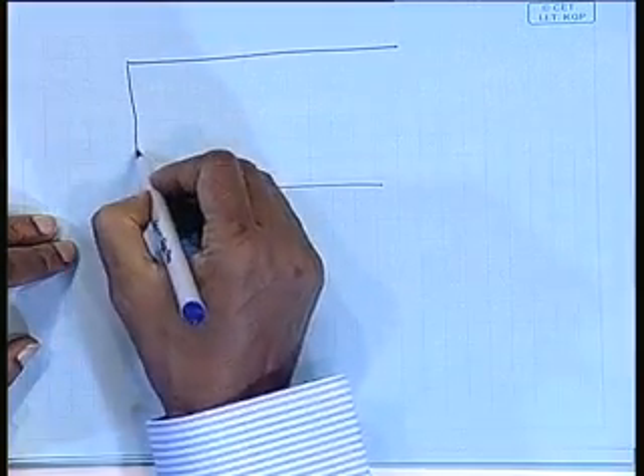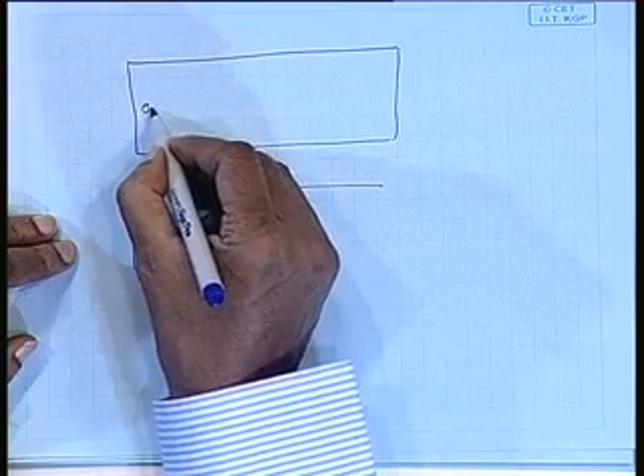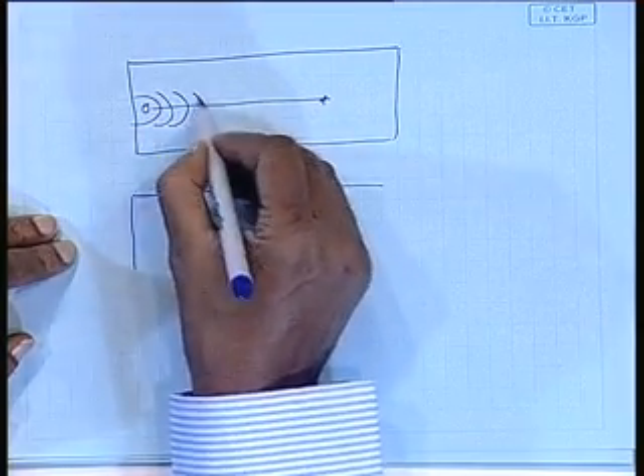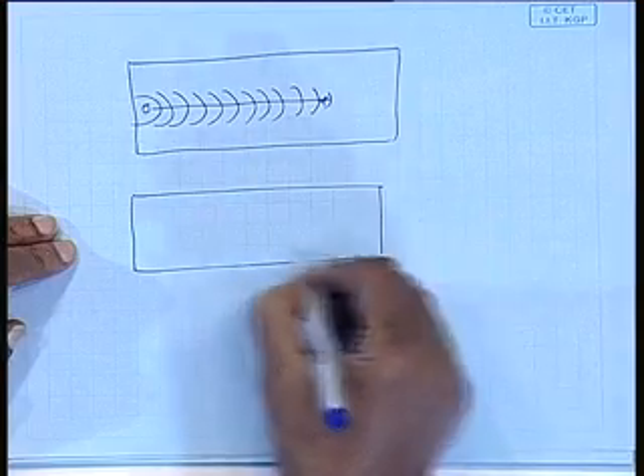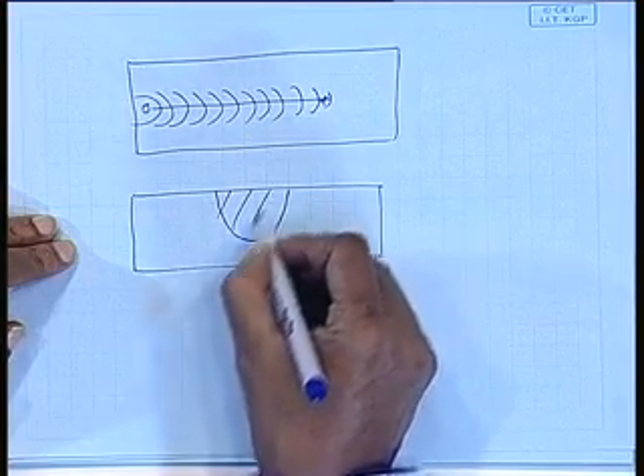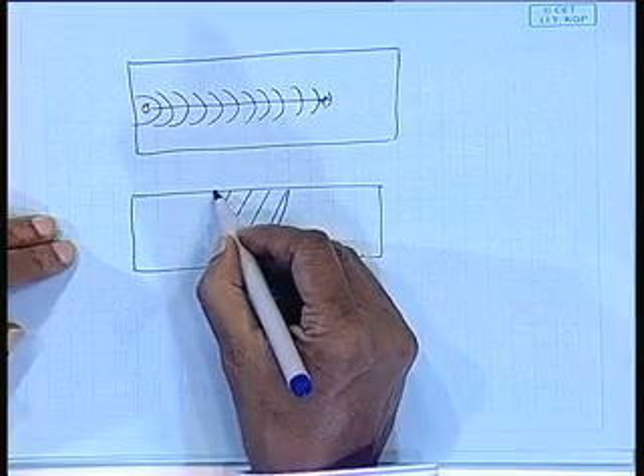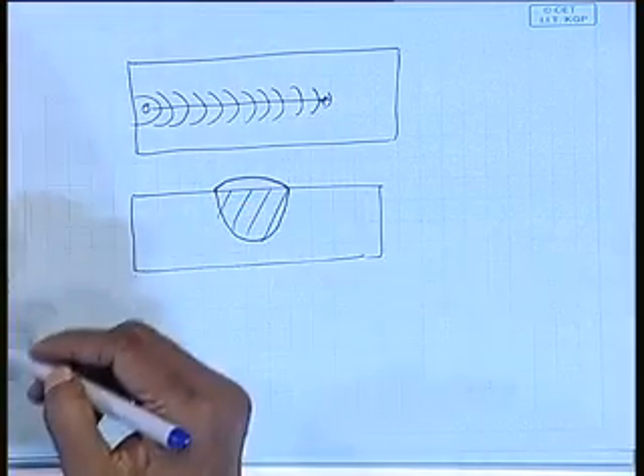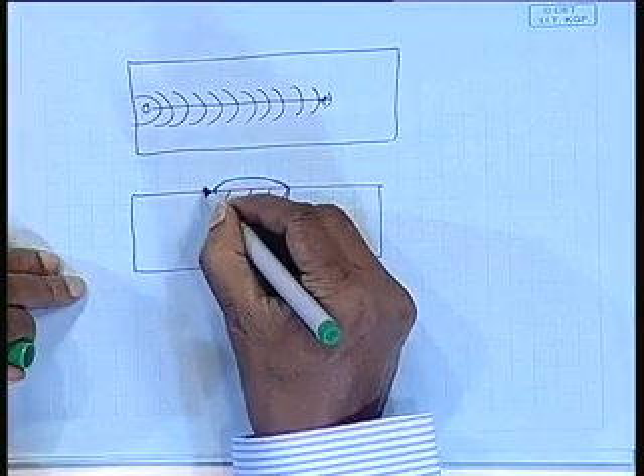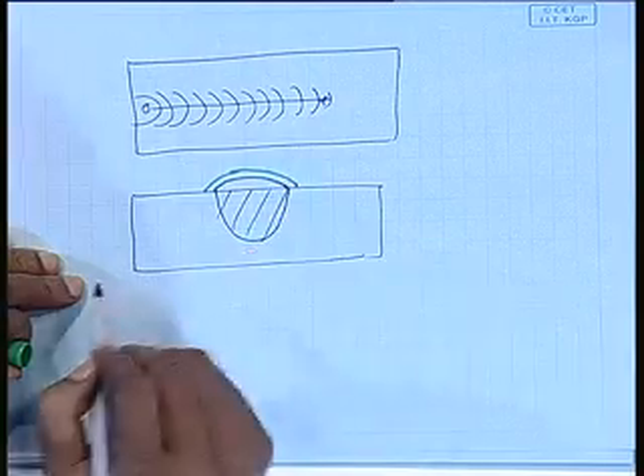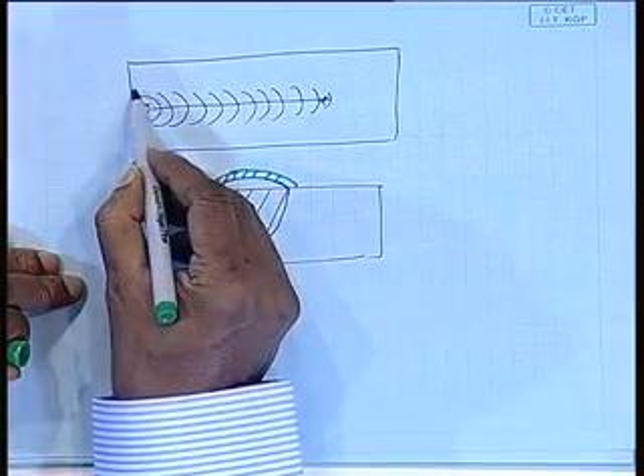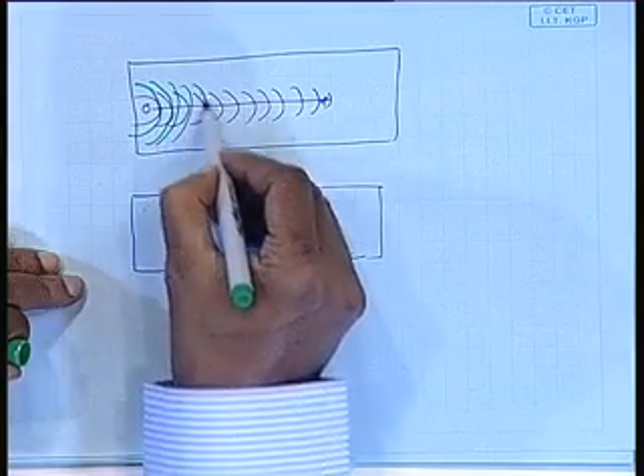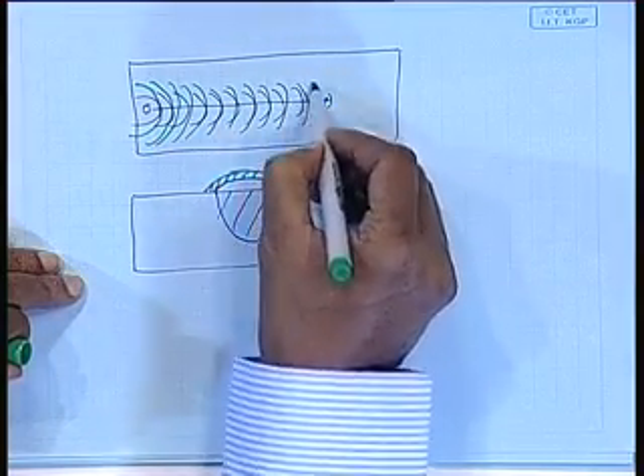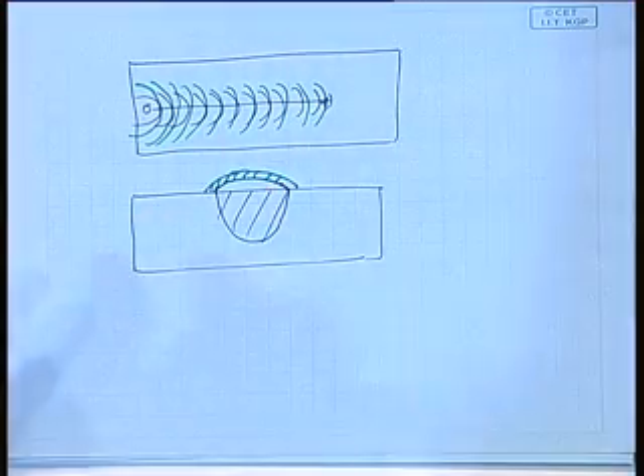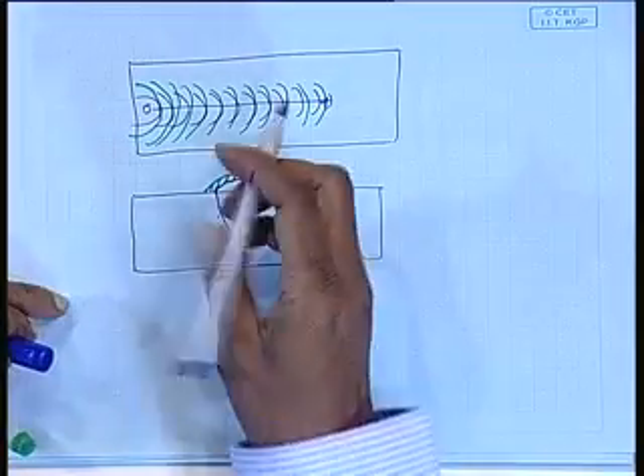Well, suppose this is my plan view. The electrode is moving along this direction. So, the deposition is taking place, right, and if I see in the cross section, suppose this is where fusion has taken place, this is the metal deposition at the top, and then over that you will have a layer of slag like this. This is the slag, means as you are going past, these green lines, I am referring to the solidified slag. It will solidify, right, and then on top of that you will have these granules.